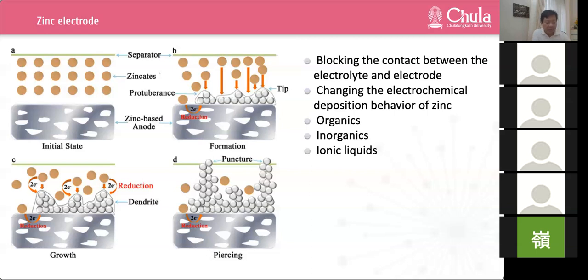Generally, dendrites are axial and needle-like single crystal with flat step top. The growing dendrites will cause the battery short circuit and deteriorate electrochemical performance, which results in a short battery life. In addition, dendrites are easily detached from the electrode, resulting in attenuation of the battery capacity. And the harm of dendrite growth to the battery can be mitigated by physically blocking the contact between the electrolyte and electrode, or by changing the electrochemical deposition behavior of zinc in the electrolyte.